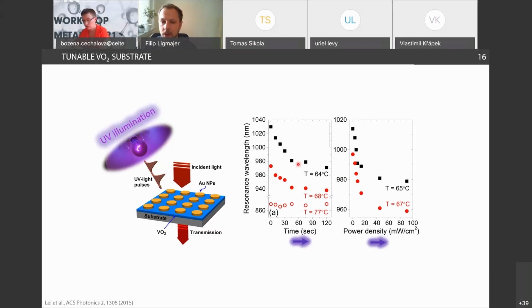So it's not totally non-volatile because you still need to keep the temperature above room temperature, but if you use UV light, you can basically keep the VO2 shifted for quite a long time, which is a nice feature, I would say.